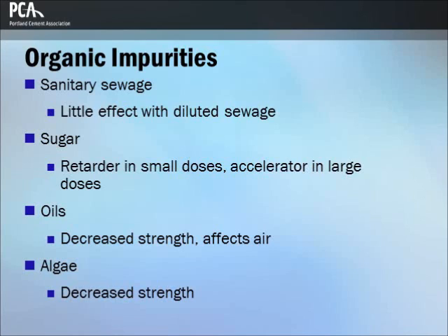Sugar, in quantities of 0.25% or more by mass of cement, may cause rapid setting and a substantial reduction in 28-day strength. Mineral oil not mixed with animal or vegetable oils may have less effect on strength development than other oils. However, mineral oil in concentrations greater than 2.5% by mass of cement may reduce strength by more than 20%. Oils may interfere with the action of air-entraining admixtures. Water containing algae is unsuitable for concrete because the algae can cause an excessive reduction in strength.